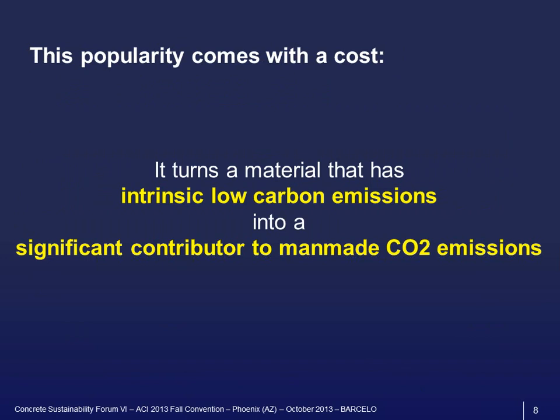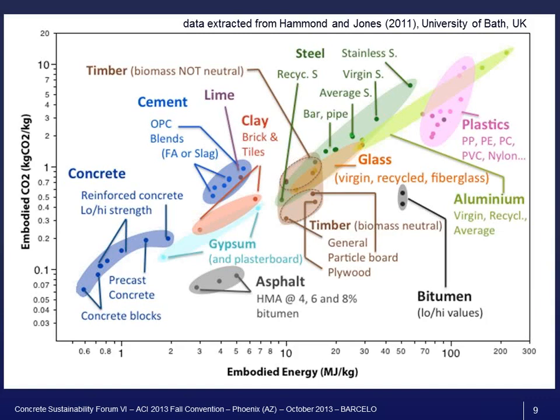Because if you look at it on a per ton basis, I put on this graph results I extracted from a study from the University of Bath in the UK. We have on this axis the CO2 footprint, and on this axis the energy footprint. And again, these are powers of ten on each axis. And you can see that concrete here is very, very well positioned: very low CO2, very low energy.